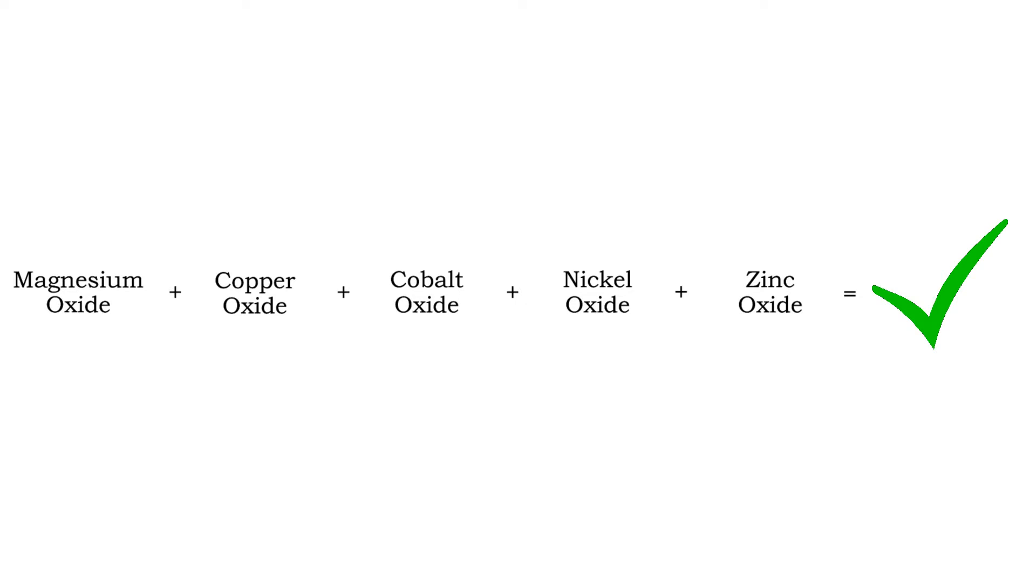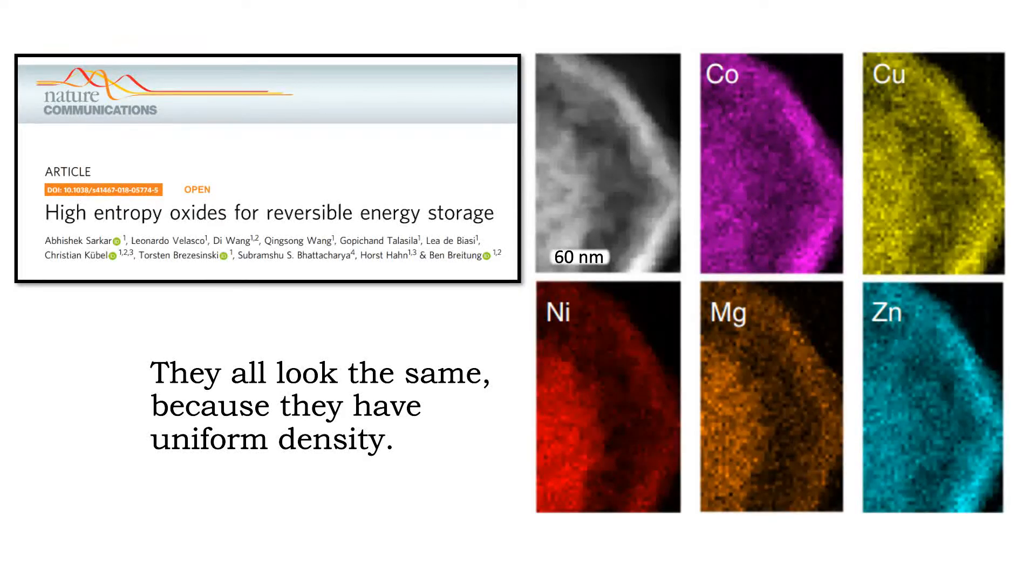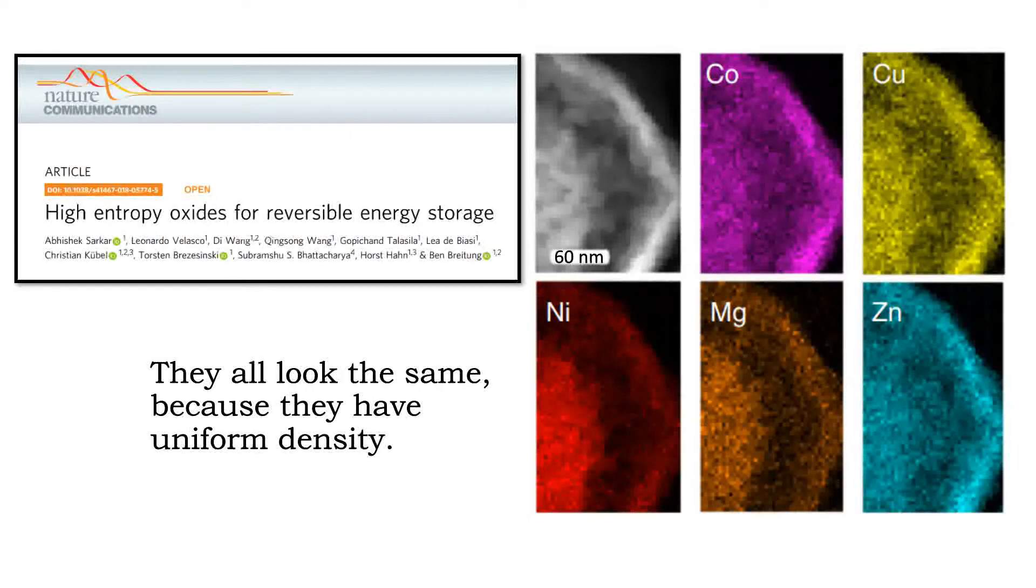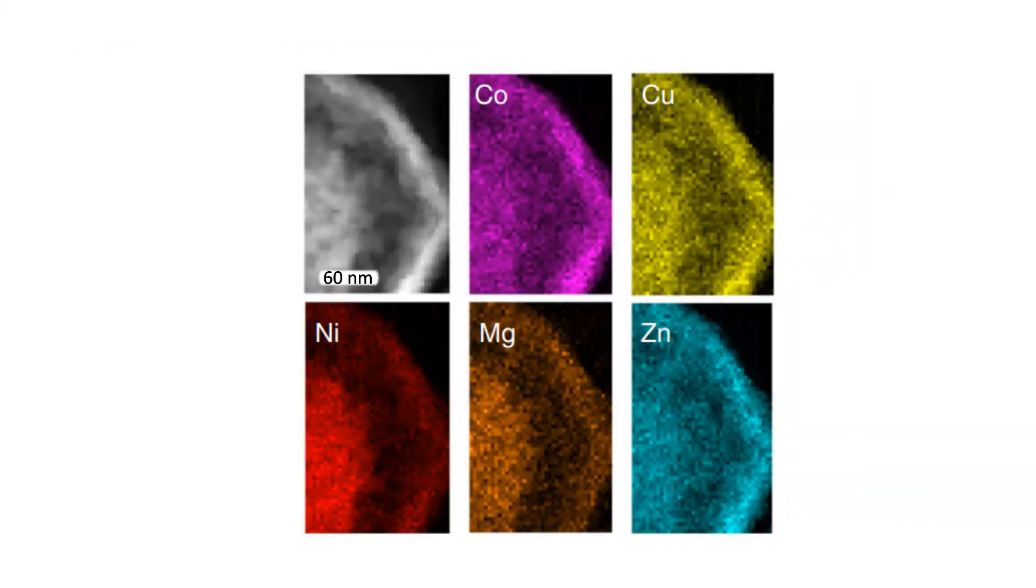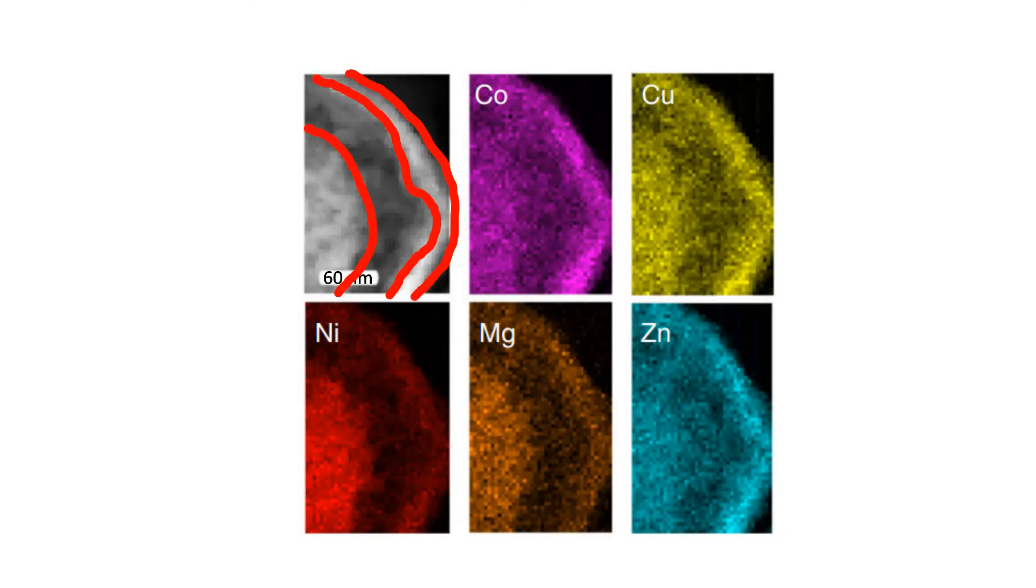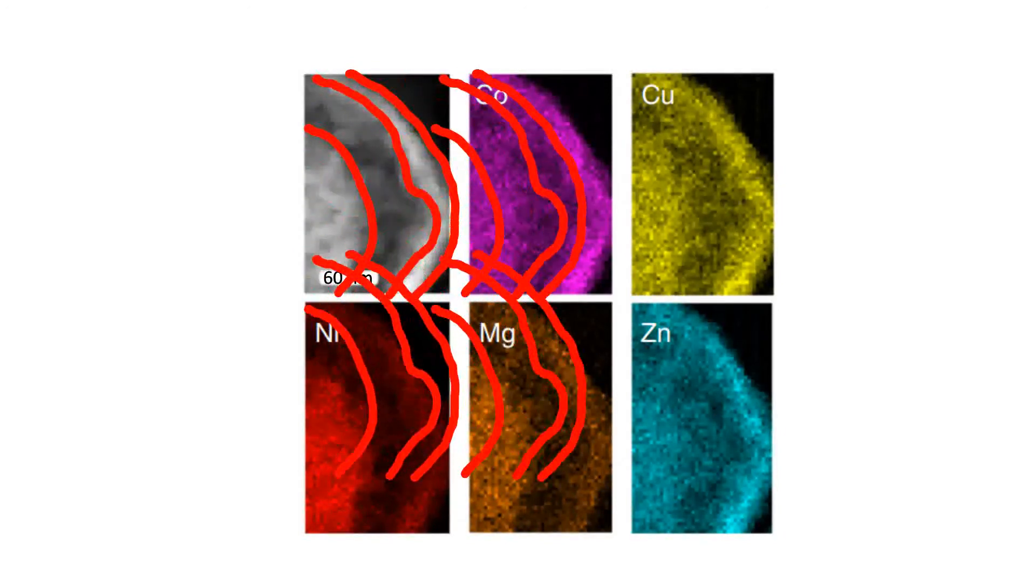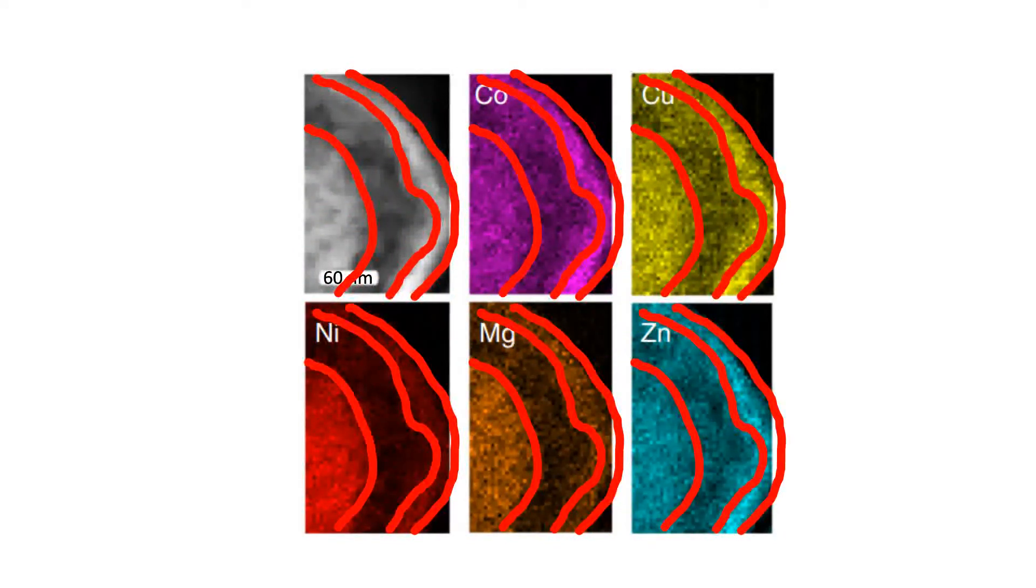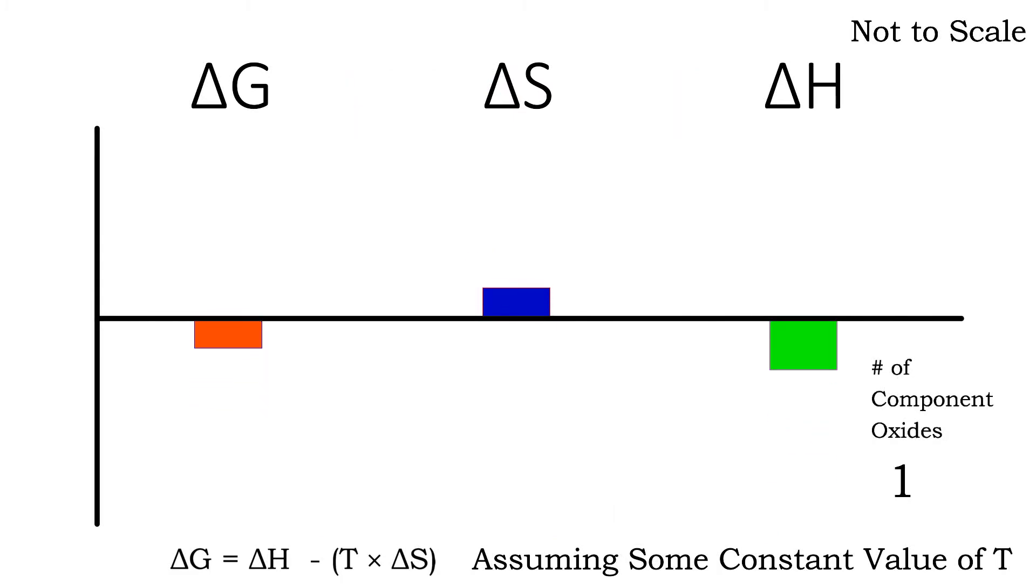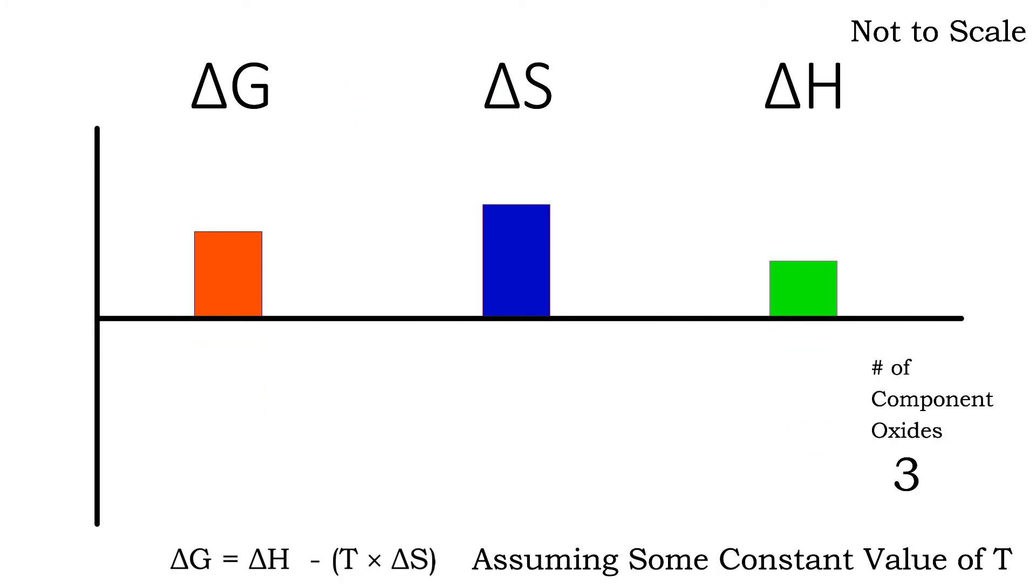These mix together, and we get this lovely smooth single phase. These images show where the elements can be found within the solid solution. They will occupy the same volume in uniform density, with a random configuration. The entropy of mixing all these cations outweighed their enthalpic cost, ultimately allowing it to stabilize.